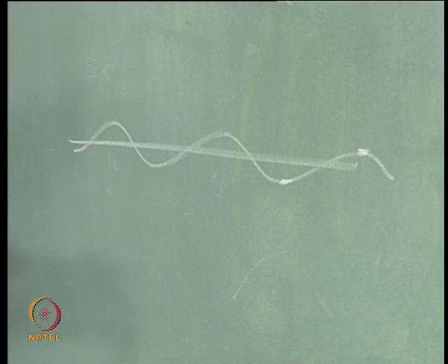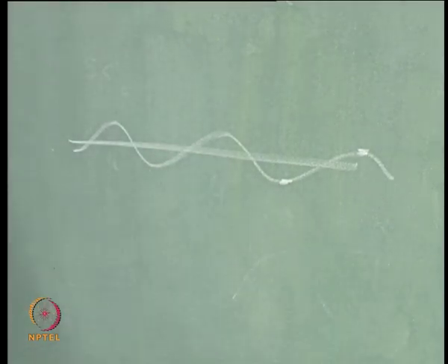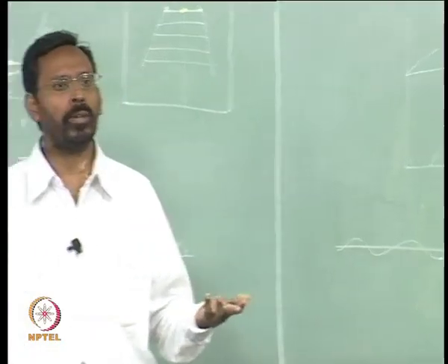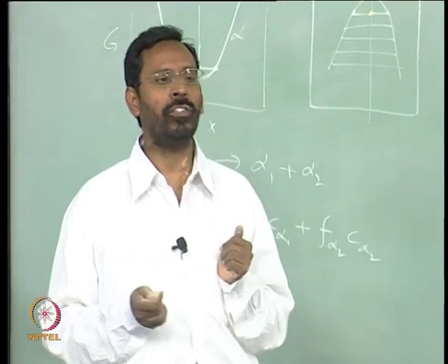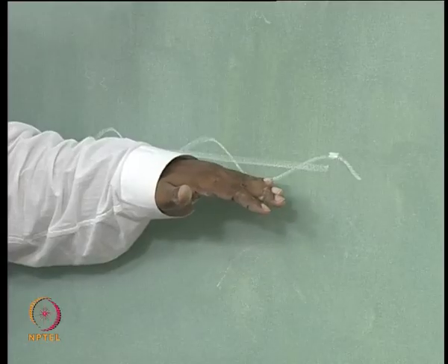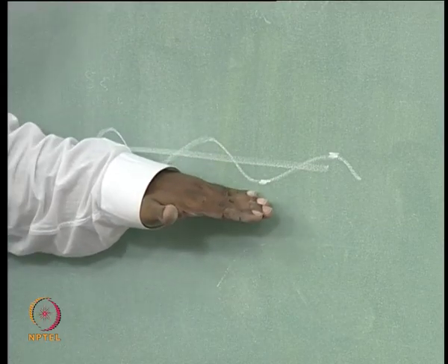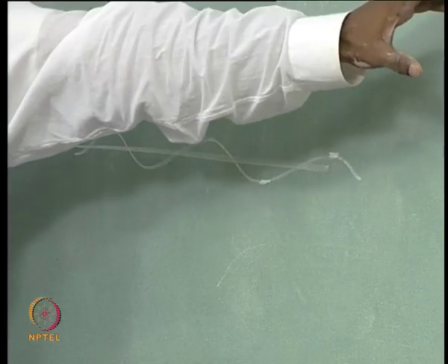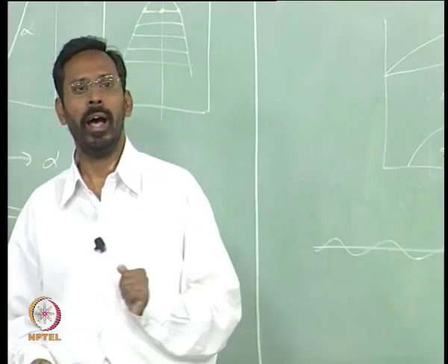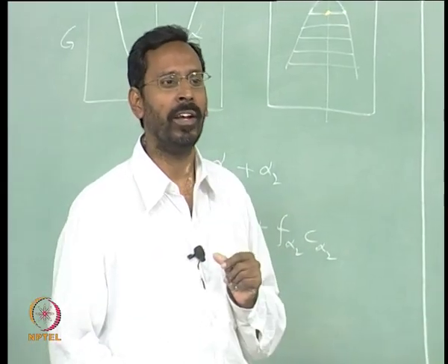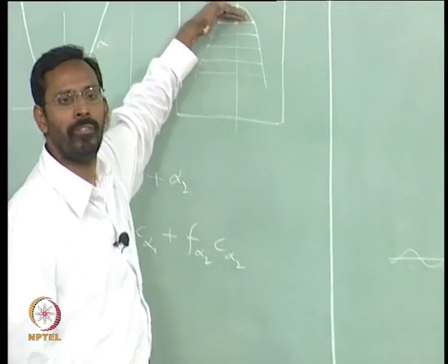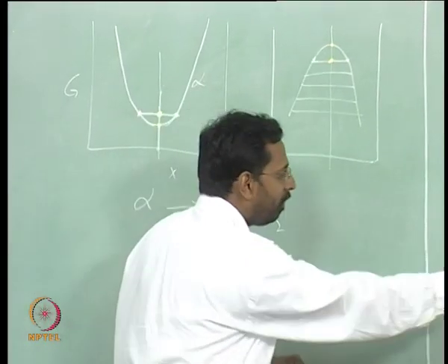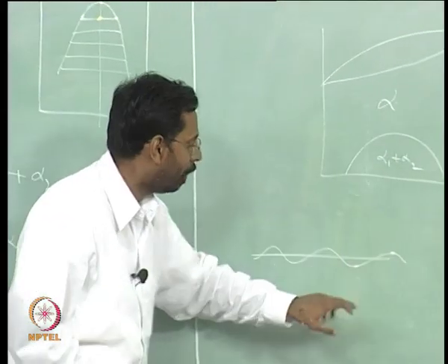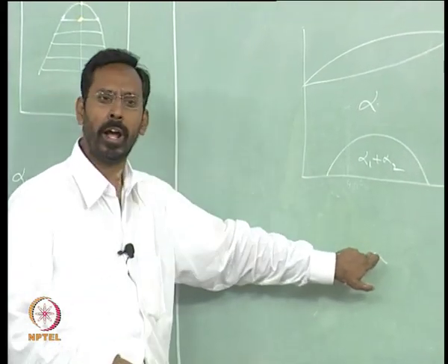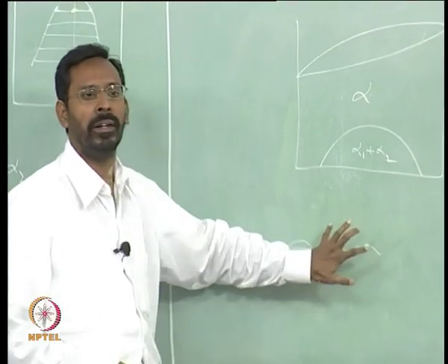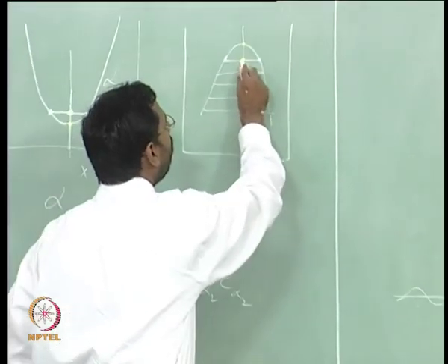So, at less than a nanometer scale, you see a small region where the atoms, because there are always atoms moving at any given temperature unless you are at absolute zero, because of these atomic fluctuations, you can see a region where the composition goes slightly below the nominal composition, and obviously those atoms have to move somewhere else. So they go to some other region where the atoms are more than the nominal composition. Once this happens, this kind of fluctuation is a stable fluctuation, because the moment such a change happens, this region with a lower copper content and this region with a higher copper content will be a stable couple, because that has resulted in a decrease in the free energy.